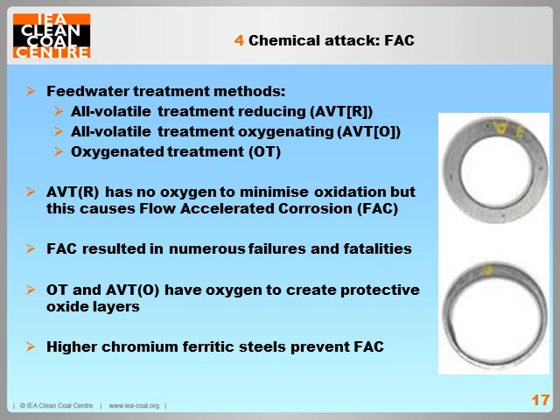The alternative is oxygenated feed water treatment, where this creates a protective oxide layer on the inside of the material surface to prevent it from further steam side oxidation and flow accelerated corrosion. Another way to protect against flow accelerated corrosion is with the use of higher chromium ferritic steels.